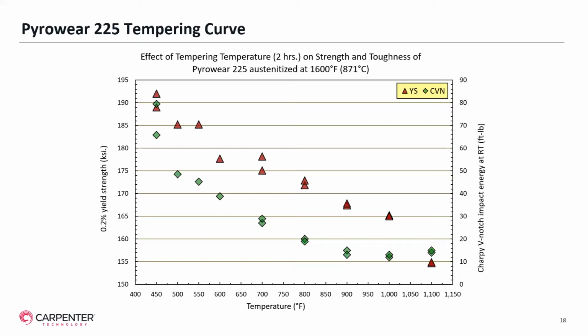At 600 degrees Fahrenheit, we're still able to offer, after tempering at 600 degrees Fahrenheit, approximately 177 yield strength and impact toughness of about 40 foot-pounds. Both of those values continue to decline if the alloy is tempered at temperatures greater than 600 degrees Fahrenheit.